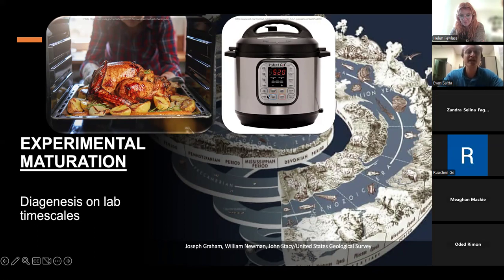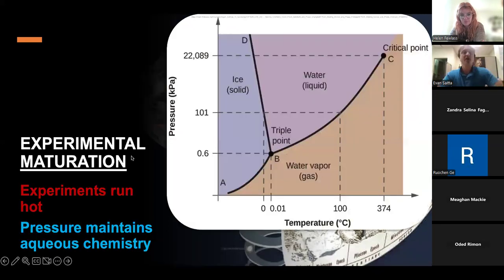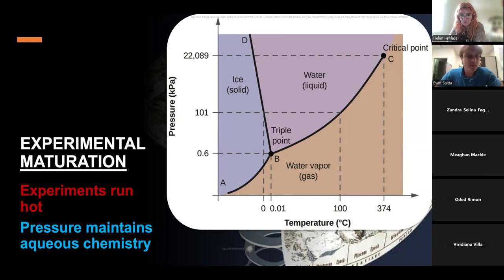And so using heat and pressure, you can simulate degradation on shorter time frames. And so we run our experiments hot. The temperatures we use in these experiments are higher than what these fossils would otherwise experience, but that's to account for time. And the reason that we increase pressure during this cook is so that you maintain aqueous chemistry. You keep water in the liquid phase, so that you continue to do the proper aqueous chemistry, as opposed to desiccating out the sample.